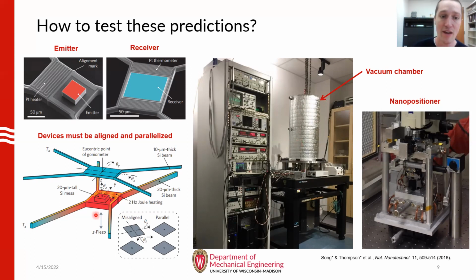Okay. So once in high vacuum, we could heat up the emitter by several degrees and then measure the temperature rise of the receiver. And we could do this while also systematically stepping the emitter towards the receiver until contact. And we could do this with a piezoelectric actuator, which allowed us to adjust the gap in steps of around 2 nanometers. Okay, so from these measured temperature rises, we could estimate the radiative conductance between the planar pads.